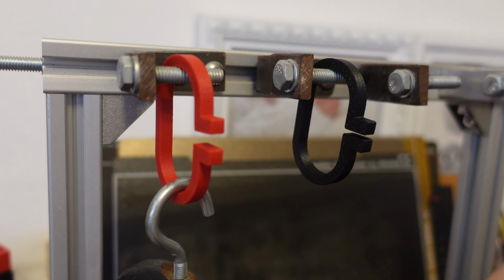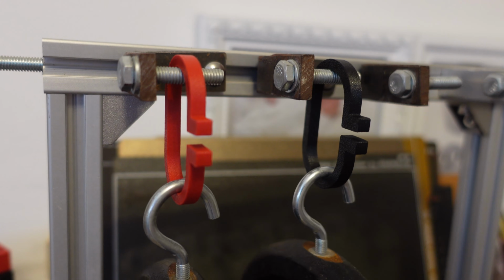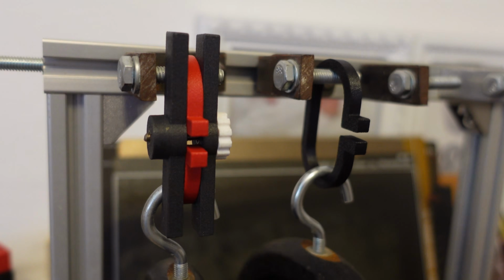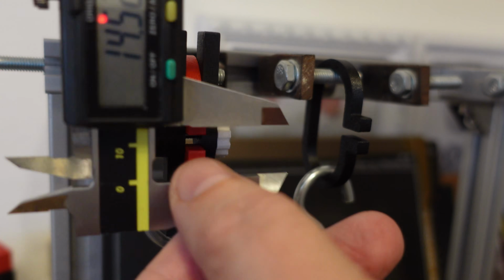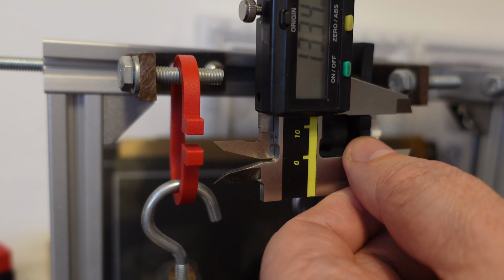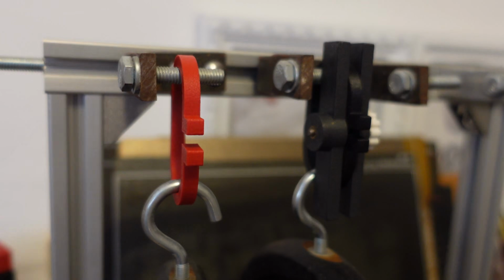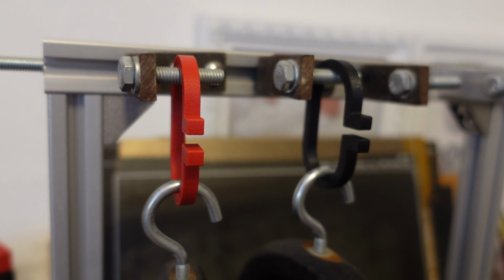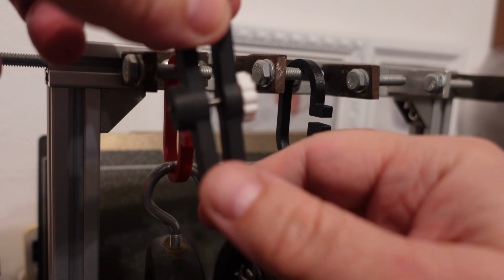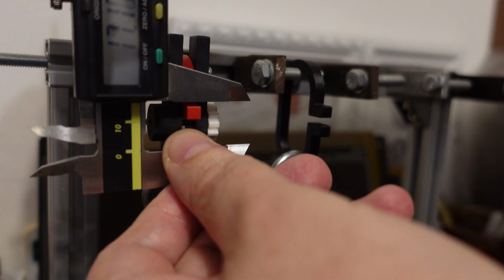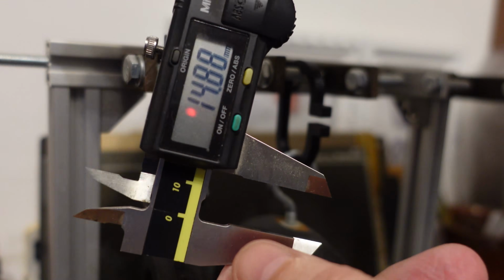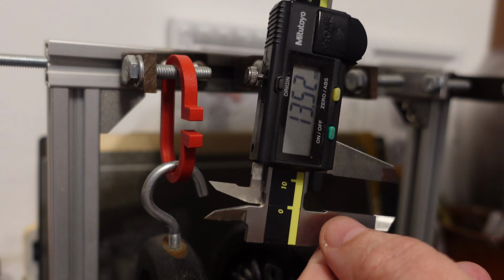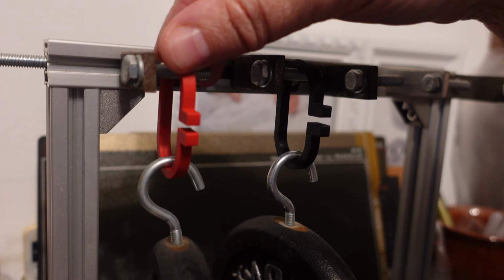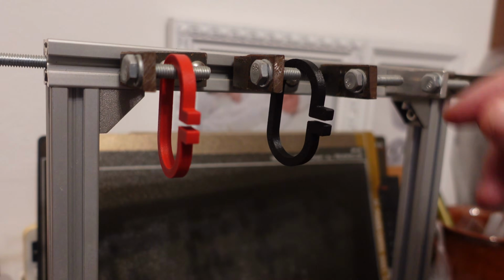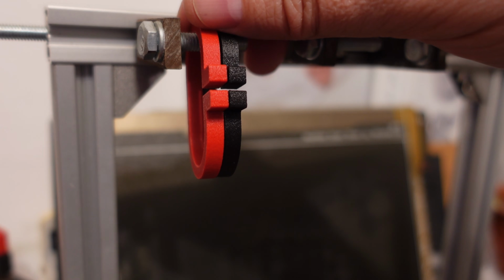Creep test, the deformation under constant load of 1.25 kg, locking the position for more accurate measuring. 14.52, 13.34. Day 5, the last measuring. 14.88, 13.52. Let's remove the load. Permanent deformation is very minimal and almost equal.